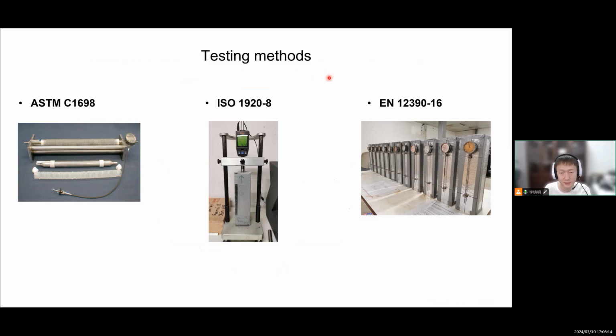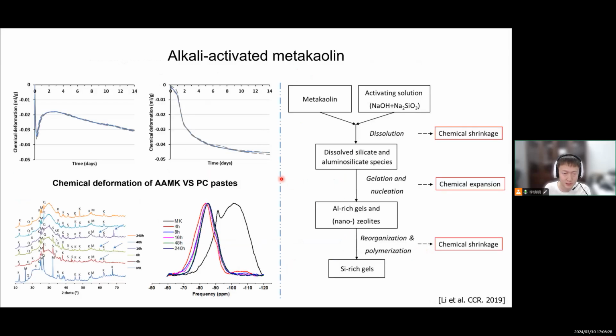First, about the testing method, basically the methods developed for Portland cement work for alkali-activated materials, which are also binder materials. Except for the alkali-activated metallurgical slag system, because through experiments I found that there is not only chemical shrinkage, but also some chemical expansion. So that's the reason why I propose to use the term chemical deformation rather than chemical shrinkage, because there is possibly an expansion there. And this is intrinsically different from Portland cement.